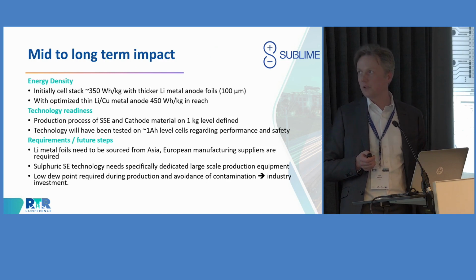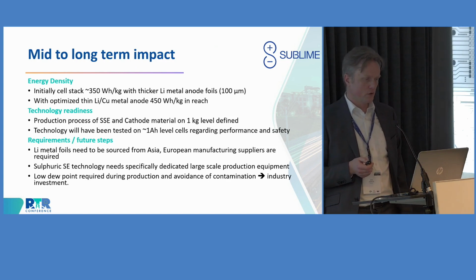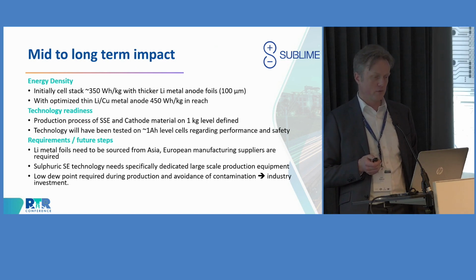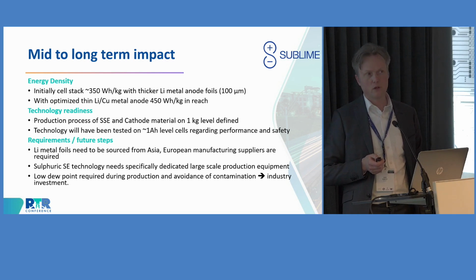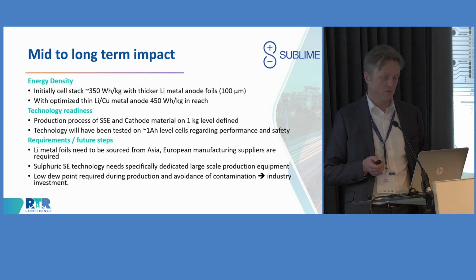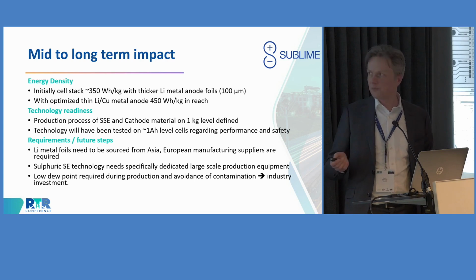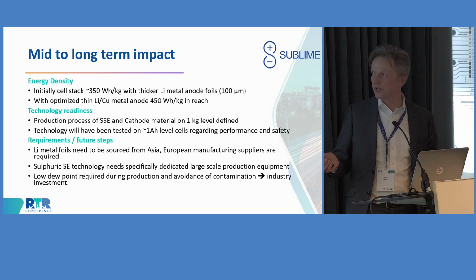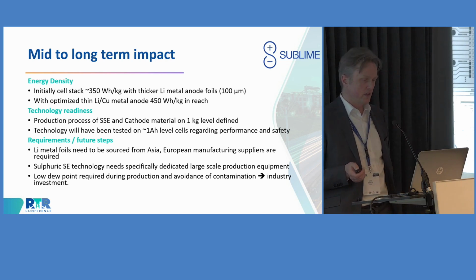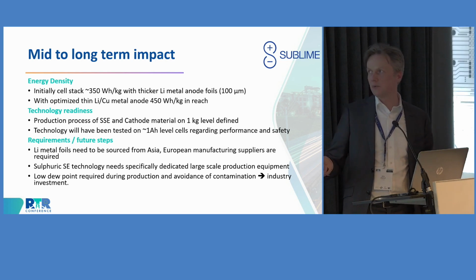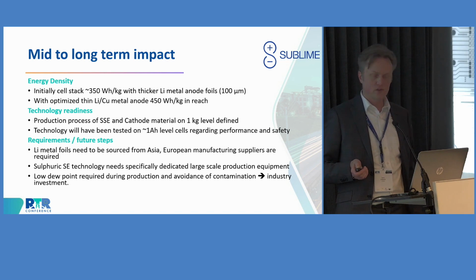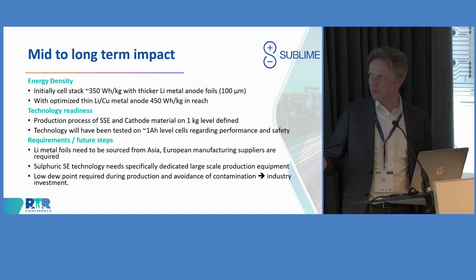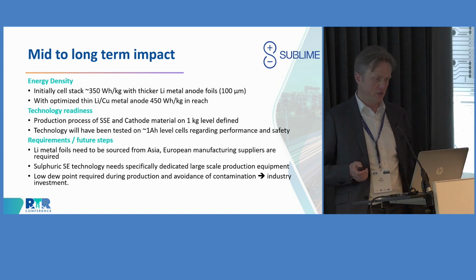Now, I would like to come basically to the conclusions of this project. We see in terms of the mid to long-term impacts, that of course, we have some problems in order to source the correct material for the anode side at the moment. So we have to use the thicker material for the lithium. That would mean that we would target with that material only a lower energy density first. And once we have resolved the problems, then with the thinner and optimized lithium copper metal anode, again, we would be able to reach the high energy capacity.